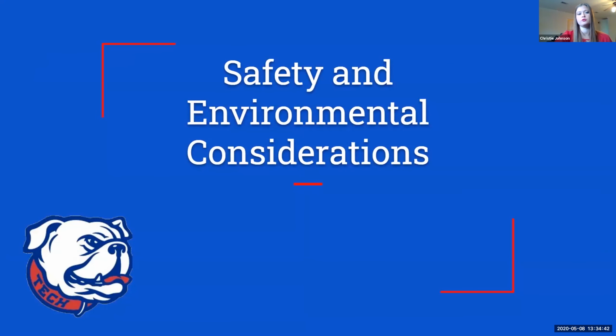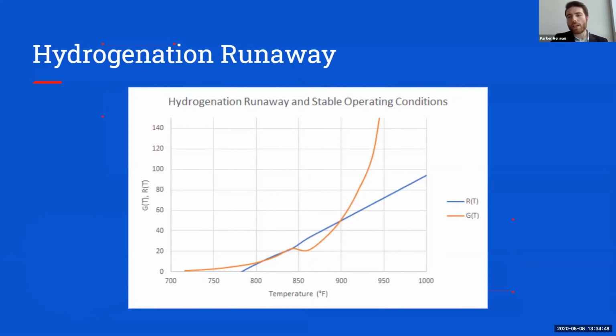So now Parker's going to talk a little bit more about our safety and environmental considerations. So one of the main hazardous issues with this system specifically is the chance of hydrogenation runaway due to the hydrogenation reactions being exothermic. And so as you can see on this heat generated versus heat release graph, once you reach around 900 up to 1,000, it does pose a problem because your generated heat outweighs your removed, and so then your temperature would just essentially continue to increase within your reactor, and it could lead to several issues such as an explosion if the temperature were to get too high.